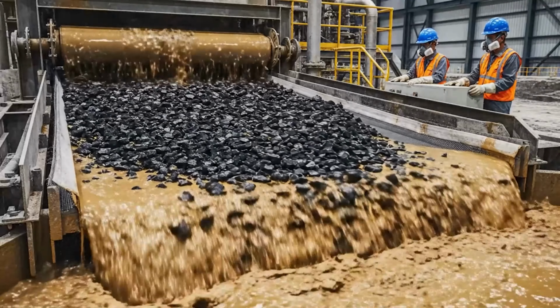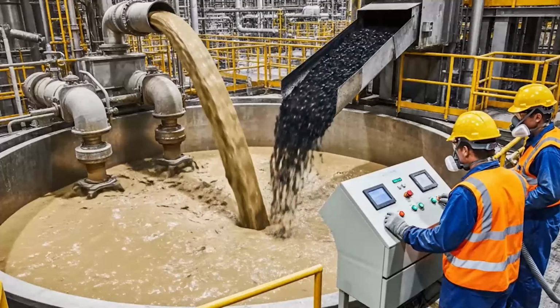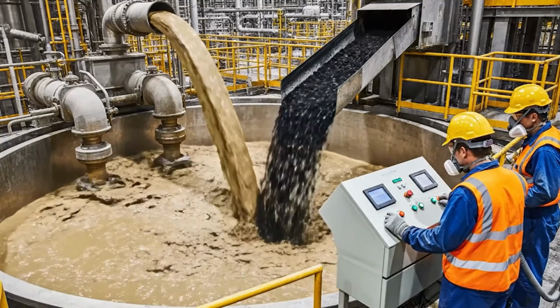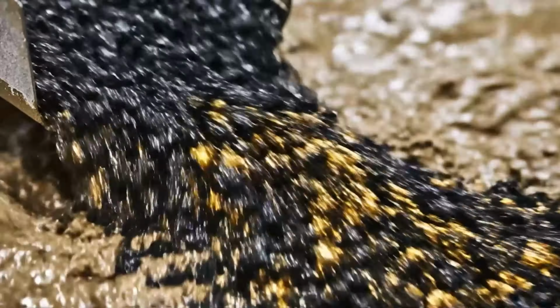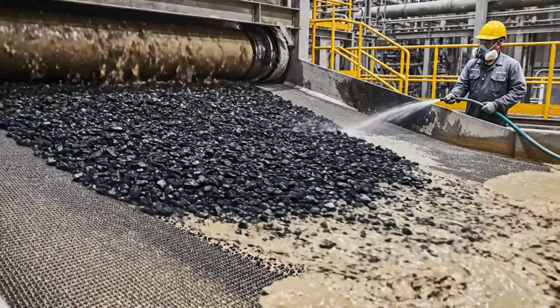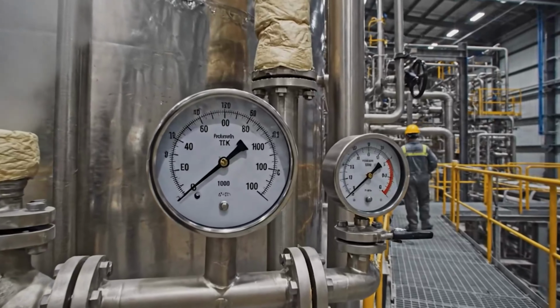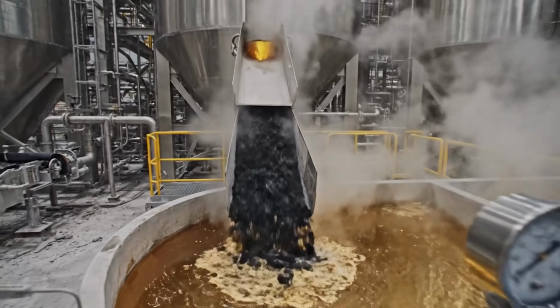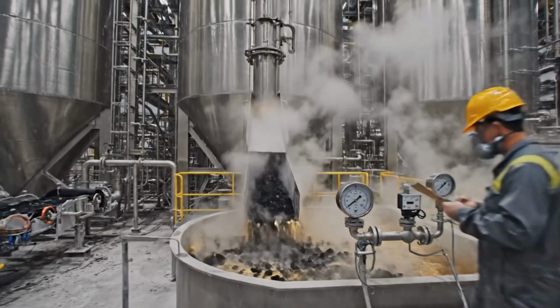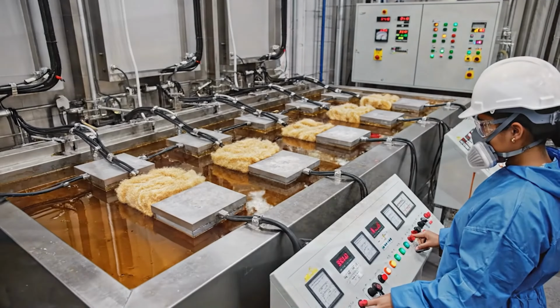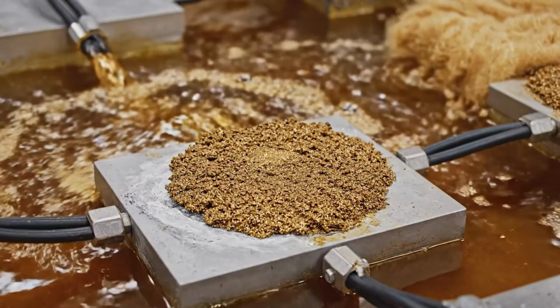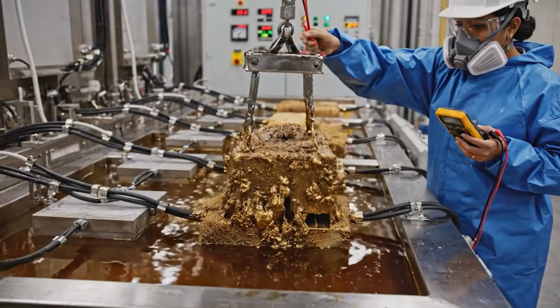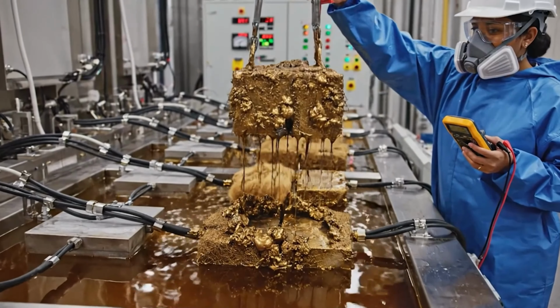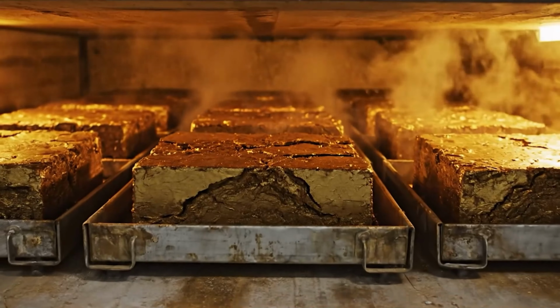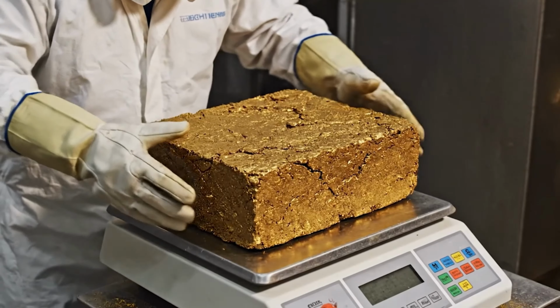Carbon in pulp, CIP, or carbon in leach, CIL. Activated carbon adsorbs the gold complex like a sponge. Loaded carbon is stripped with hot caustic cyanide solution in elution columns. Then, electrowinning. Electric current forces gold to deposit as a brown sludge on steel wool cathodes. The sludge is filtered, dried, and ready for smelting.